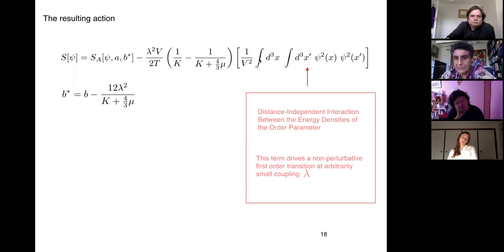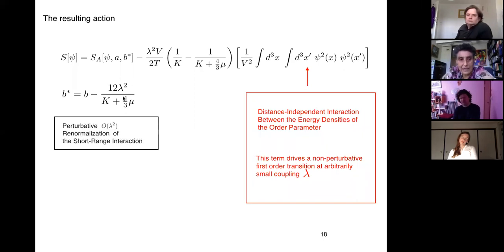Now, let's look at this other term. Notice a couple of things. First of all, it's a distance independent interaction between energy densities of the order parameter. It's highly non-local. This term is all local. This is highly non-local. So it's a distance independent interaction between the energy densities, and it's this term that drives a non-perturbative first order transition at arbitrarily small couplings. Now, it is true that we have a perturbative term of order lambda squared that leads to a renormalization of the short range interactions. But since the Larkin-Pikin effect is for arbitrarily small lambda, this is not that important. And in what follows, I'm not going to distinguish between B and B tilde, B star.